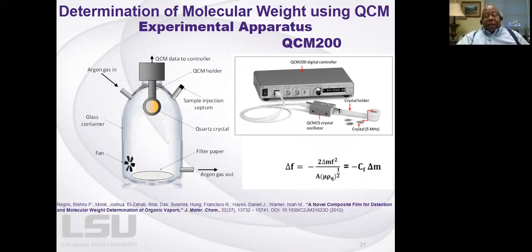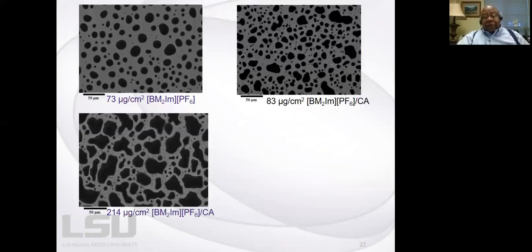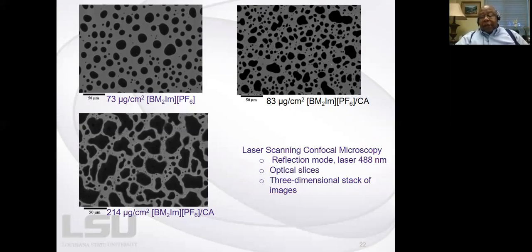And this is what the surface looks like on that particular crystal. So we put different ionic liquids on that. You'll notice that these are different ionic liquids with different, well, I'm sorry, this is the same cation here, but different thicknesses. We used laser scanning confocal microscopy to get these images of what the surface is like. The surface maximum heights on these particular materials are 2.6 micron, 2.8, and 3.2 micron.